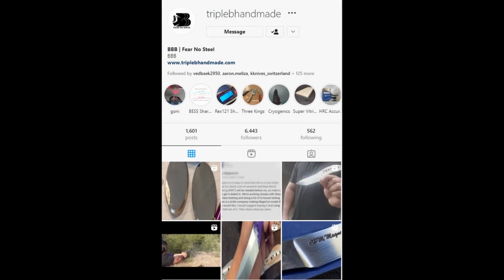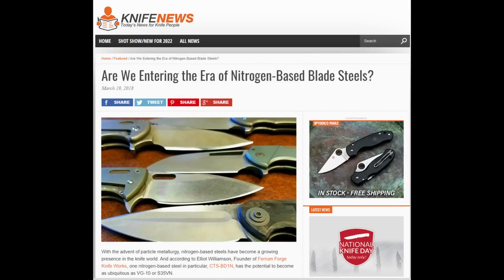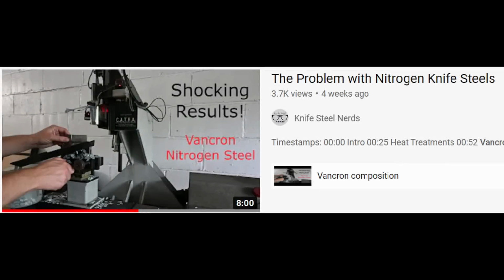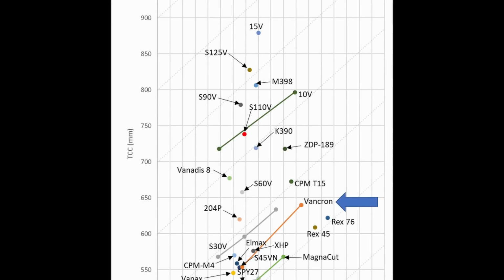So we're going to discuss some experiments I did recently on nitrogen knife steel. Nitrogen is the hot thing these days. Maybe not so much anymore. A few years ago, it seemed like there were a bunch of articles about nitrogen knife steels being the future. And I had an article and video a few weeks ago about Vancron, which is a high vanadium non-stainless nitrogen knife steel. And the big surprise with that study I did was that the edge retention wear resistance was much lower than other high vanadium steels from the nitrogen rather than carbon. So that the vanadium carbonitrides are softer than vanadium carbides.